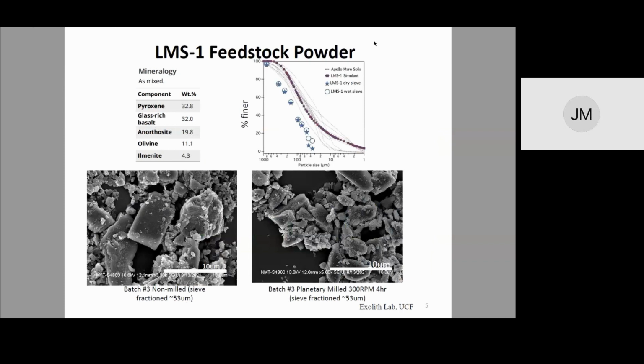So the bottom left SEM image is of the newest batch that we have received, sieve fractioned to 53 microns, not milled. So we took it out of the bag, sieved it, and then put it under SEM. The second one on the right is more of a milled sample. So we milled it at 300 RPM for 4 hours in a planetary mill, and also sieve fractioned it to 53 microns. You can see that there's a modest particle size reduction in the larger particles, but the number of fines stays consistent. Next slide, please.